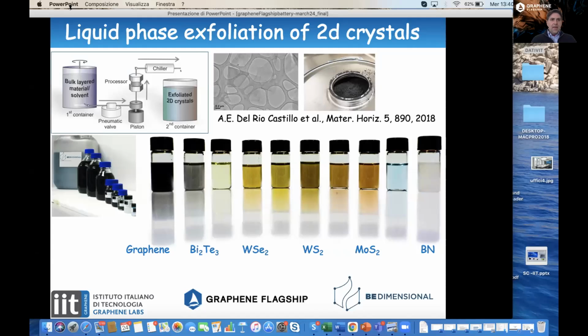which is a very small chamber with a given dimension where, in light of the pressure, there is turbulence in the liquid, and the turbulence gives rise to shear forces, and the shear forces are able to exfoliate graphite into few layer graphene. And this method allows the production of large quantities in short time at